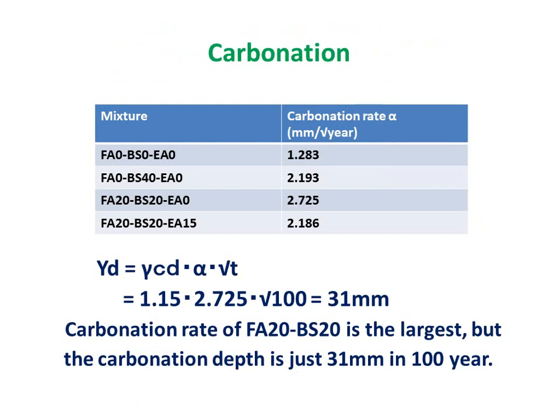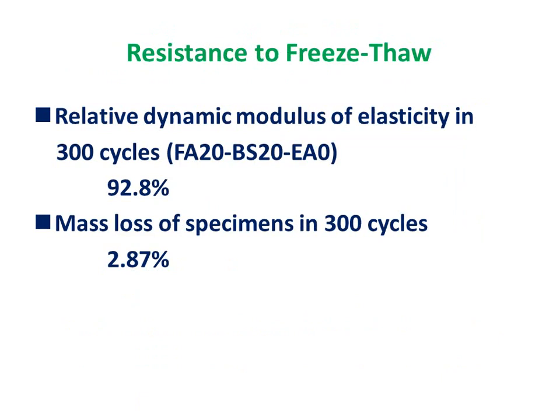carbonation. So the carbonation rate, FA20-BS20, was the largest. But the carbonation depth is just 31 millimeters over 100 years. So it means that we can ignore the carbonation performance. And for resistance to freeze-thaw, we got the relative dynamic modulus of elasticity in 300 cycles of approximately 92.8%. And mass loss was 2.87. So we don't have any problem with the resistance.